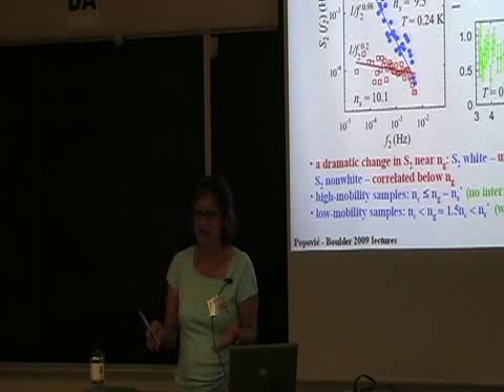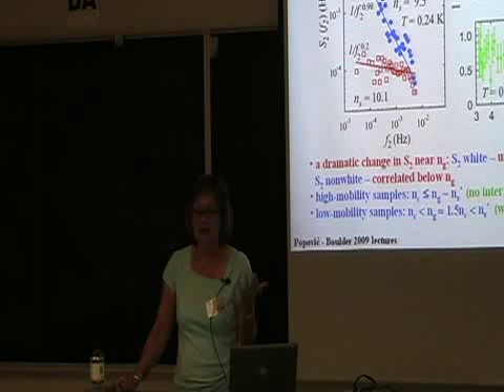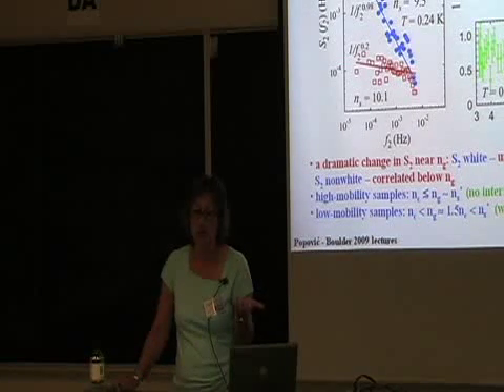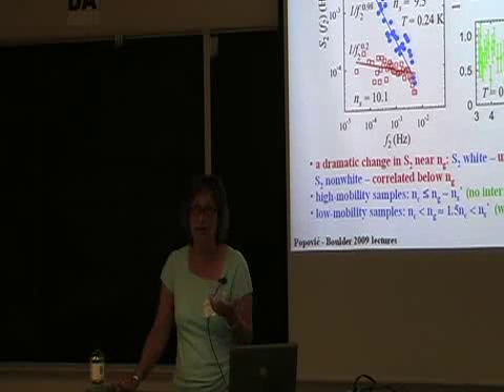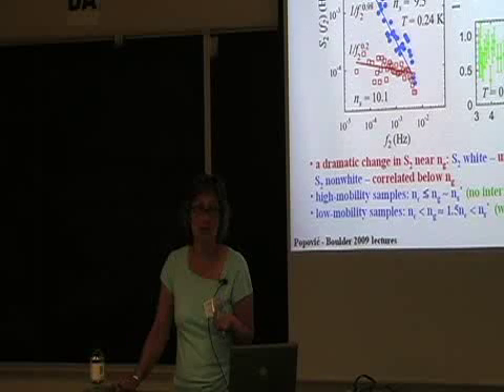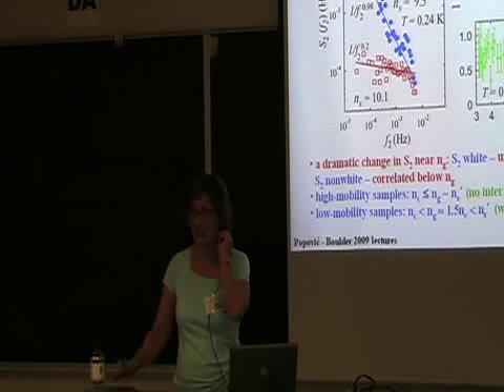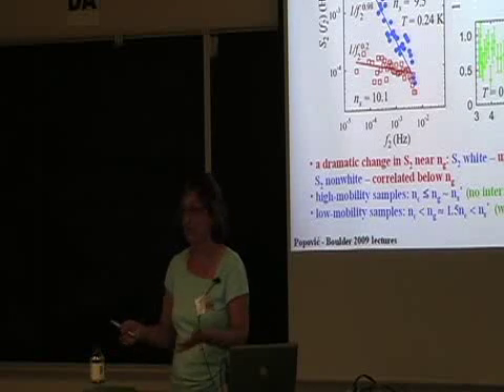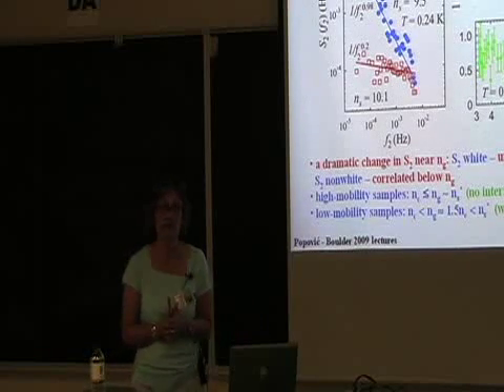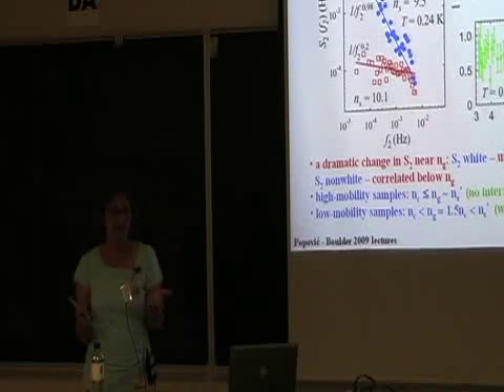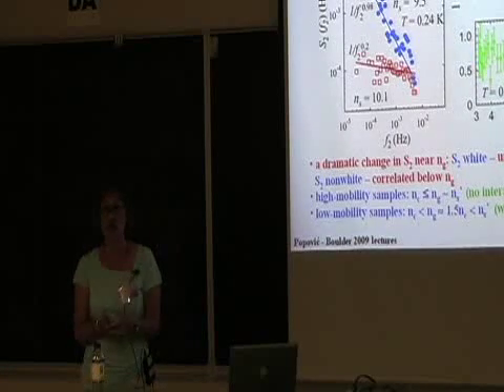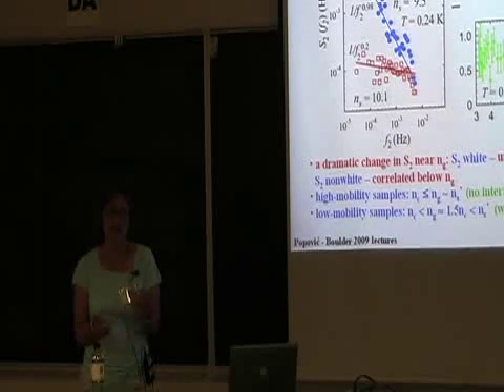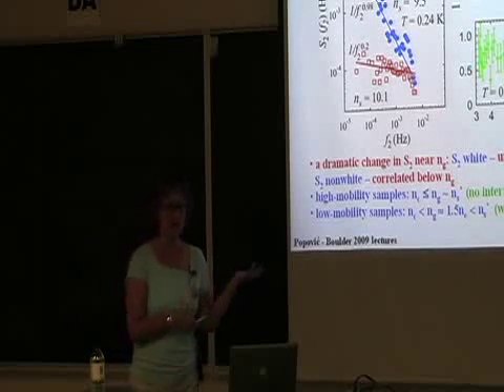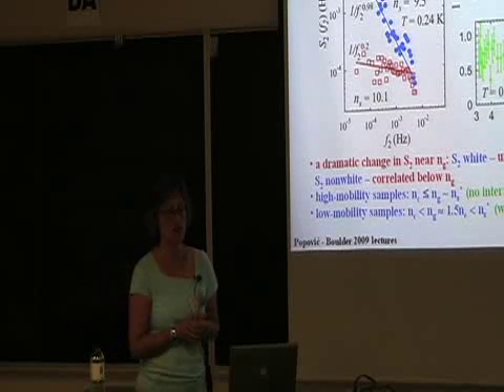Or maybe you can define it differently. But again, after the cooling down, we did not see any dependence on the cooling time. We varied the cooling times between about 30 minutes to 8 hours. We did not see any dependence on that. So this is why we needed a different time where it actually had some effect that we could control. Again, I think maybe this is because this perturbation is just so small to see change in the temperature compared to the relevant temperatures here.